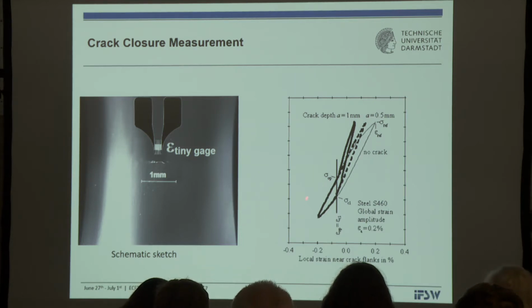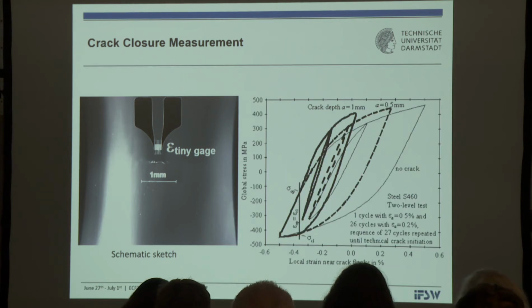And keep this figure a bit in mind, because now I perform a variable amplitude loading, which consists of a large cycle, which we have seen previously, 0.5% amplitude, and interspersed I have applied the small cycles of an amplitude of 0.2%, which we saw just before. And if you see the measuring signal here, then you see that these small cycles during their complete range are totally open, and the total range can cause fatigue crack growth. And this is a sequence effect occurring in this stage.